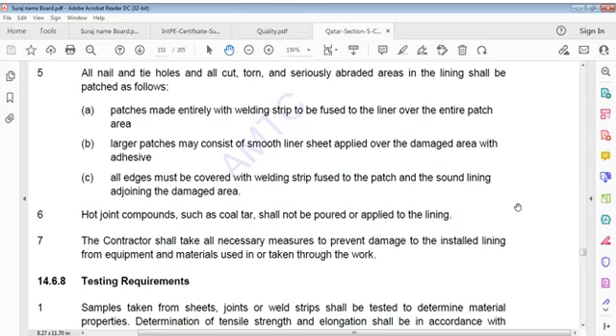and all cut, torn and seriously abraded areas in lining shall be patched in this way. Patches made entirely with welding strip to be fused to liner over entire patch area. Larger patches may consist of smooth liner sheet applied over damaged area with adhesive. All edges must be covered with welding strip fused to patch and sound lining adjoining damaged area. Hot joint compounds such as coal tar shall not be poured or applied to lining. Contractor shall take all necessary measures to prevent damage to installed lining.